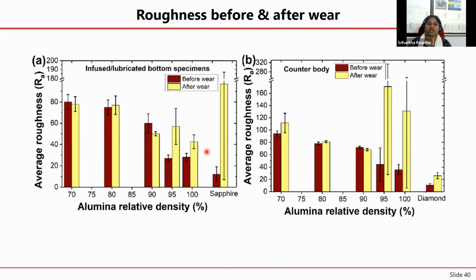Okay. So one could actually measure the roughness before and after the wear to see that, especially for the highly dense specimens, the roughness has increased dramatically because there is a breaking of the grains. However, for the other specimens, remember that these specimens already have roughness because of these debris compacted areas and some porous regions. So already they do have roughness. And now due to the wear, the roughness did not significantly increase because there was also this oil. So that has tried to decrease the debris quantity on the surface.